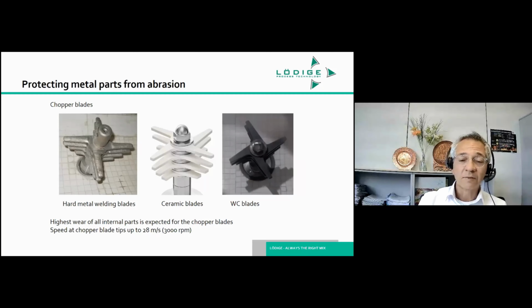Another area that needed to be looked into when handling battery masses was the high-speed choppers. These are auxiliary items and are fitted in the area of the drum where the product density is the highest. So this is the area where most friction occurs, where they do their work. So these blades are again subject to wear. And in the early days of battery mixing, the way to prevent contamination by erosion of these items was to protect the blades with the tungsten carbide metal coating.